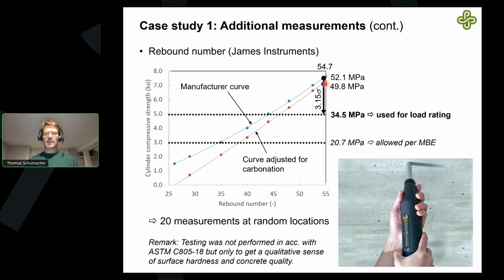We adjusted that. And then the engineer asked me, can I use about 34.5 megapascals for my load rating? And I said, based on what we see, that's about over 3 standard deviations away from this estimated curve based on the rebound hammer measurements. And we decided that we are comfortable using that value for the load rating. There was really no indication that just looking visually by the drilling combined with these measurements that should be a problem.